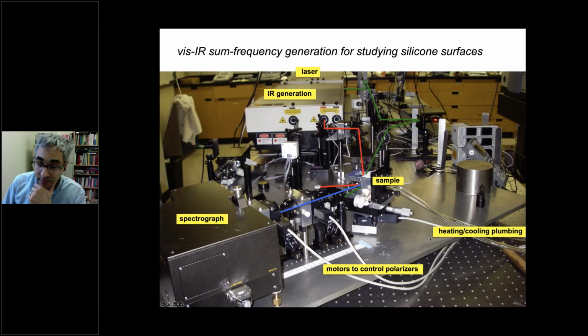So this is what the experiment looks like. It's a bit of a Frankenstein setup here. So I'm showing you in the back, there's a laser, and I just annotated this here on the slide just to show you with a green line. This is where the visible light comes and approaches the sample. And then we make a high power infrared pulse. And this is where the infrared light comes and approaches the sample. The green light's reflected off the sample. We don't care about it. The infrared light's reflected off the sample. We don't care about it because that's not the very extreme length scale we want.